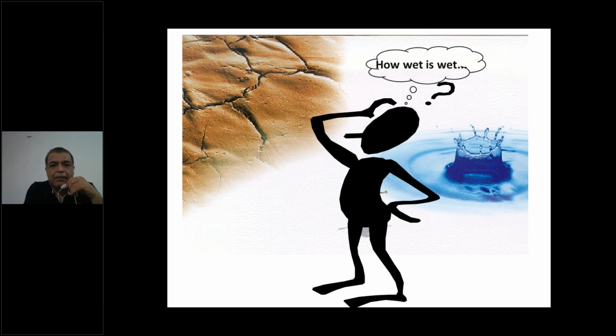The second problem comes when you etch and you dry. You can dry the enamel, that's not a problem. But when you dry the dentine, you may over dry or you may under dry. Many researchers have said you leave the dentine surface moist. Some of them say you leave it wet. Some of them say you leave it dry. So with my naked eye, I actually cannot tell how wet is wet. So it is difficult. If you have over dried, your restoration will have poor survival. If you have left it over wet, your restoration will have lesser survival.